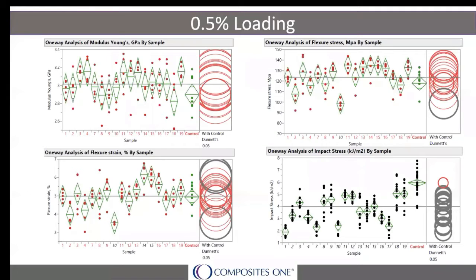Now let's also look at the toughness results in that bottom right graph. Here you'll see that all of the samples showed significant change in the toughness, but it's in the wrong direction. All of them lower the toughness of the base resin. So in result, none of these results for the 0.5% loading show any great promise for us.